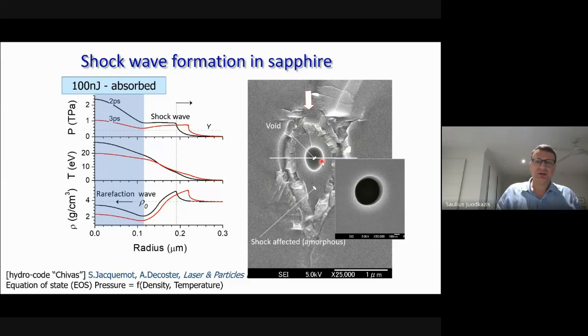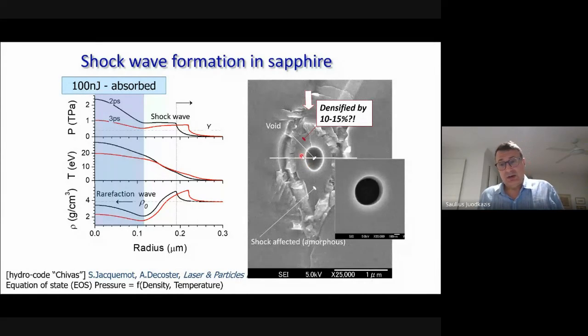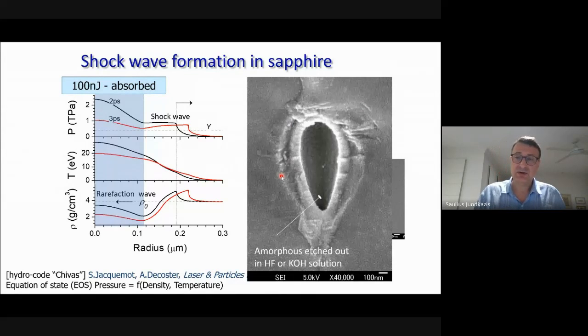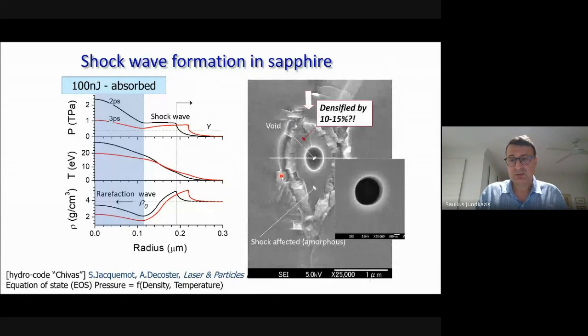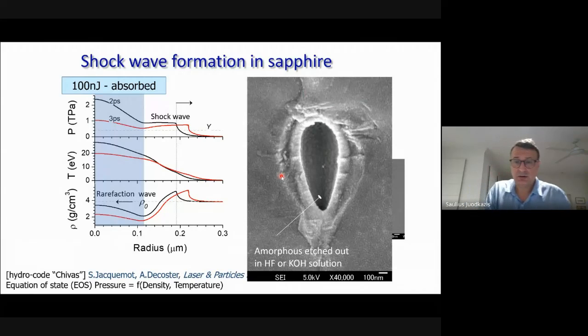From calculations, we see diameters which are twice larger than those which we saw in experiments, but this was good in terms of understanding the qualitative picture of what is happening. What is also amazing, if you think this is sapphire, and sapphire is pushed out of the center, and this is the amorphous part of sapphire, which is densified. Amorphous usually is less dense, but this is amorphous which is densified because it's squeezed against the wall, against bulk sapphire. And we know that it's amorphous because we can wash it out in acidic or basic solution.